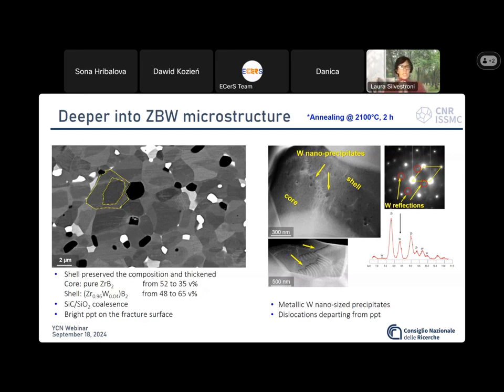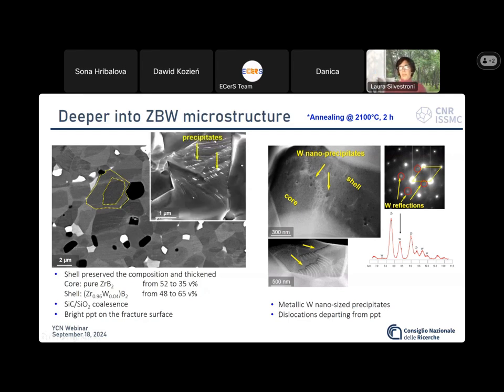There was coalescence of silicon carbide grains and, again, the bright precipitate. By TEM, we were finally able to label these precipitates as metallic tungsten, from which the dislocations departed. So we had some nano-metallic particles inside a micron-sized boride grain.